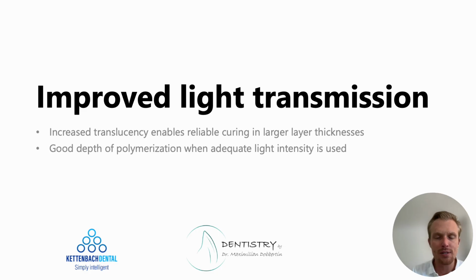Sometimes bulk fill composites, such as this particular one, do a little bit of a color shift within the polymerization, which means that initially it is a little more translucent to enable better light transmission, and with polymerization the arrangement of fillers and particles within that system then after all blocks out a little bit of light to gain more opacity and more of that opalescence dentine effect, so that the restoration can actually look quite natural.